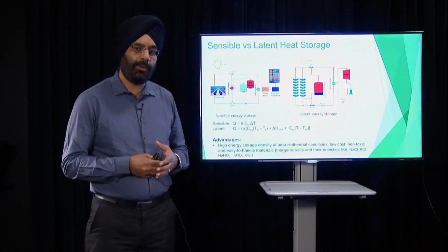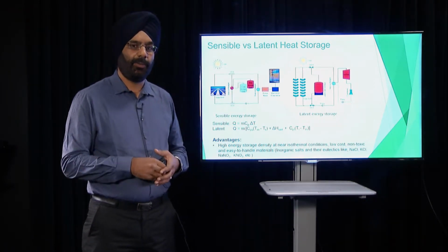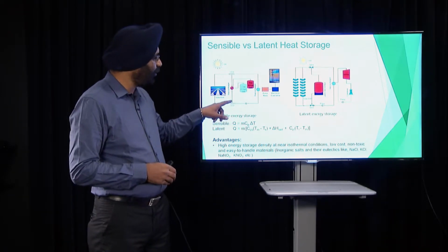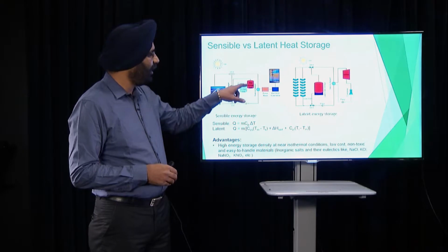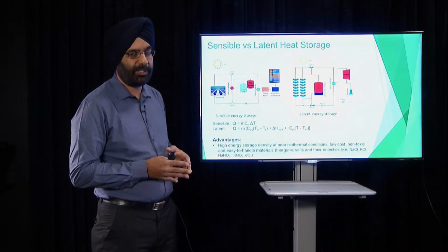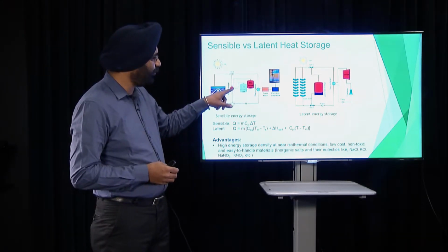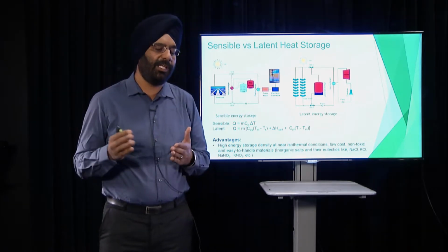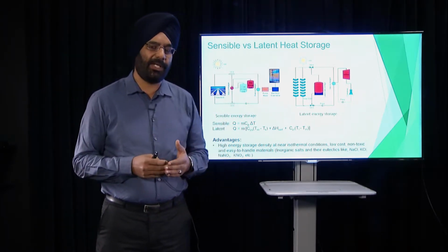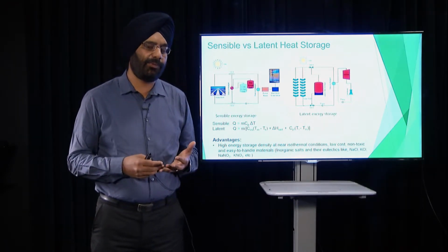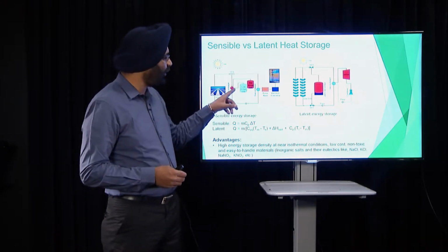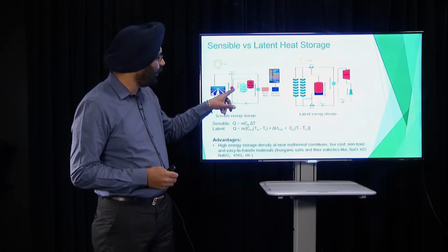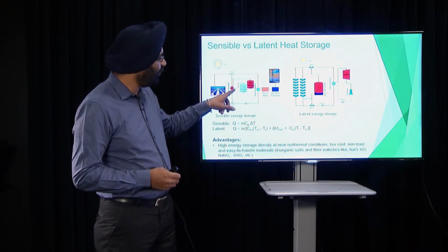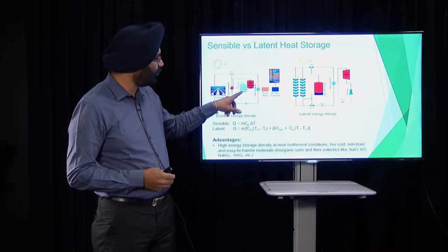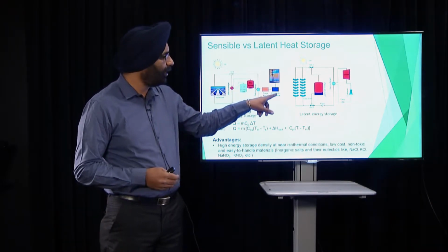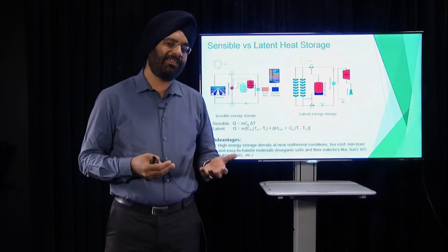And during nighttime, when sun is not available, the whole process reverses. During nighttime, the heat transfer fluid at lower temperature comes to the heat exchanger, and the hot molten salt, which is probably at 500 or 580 degrees C, or say 400 degrees C, comes at this point. Now the heat flow is in the opposite direction. So heat flows from the molten salt into the heat transfer fluid. As a result, during nighttime the heat transfer fluid is being heated, whereas the molten salt is getting to lower temperature. The molten salt at lower temperature then comes back to the cold storage tank, and the heat transfer fluid goes to the power block and generates the electricity in a normal way. So this is the sensible way.